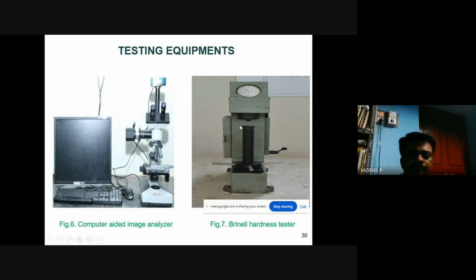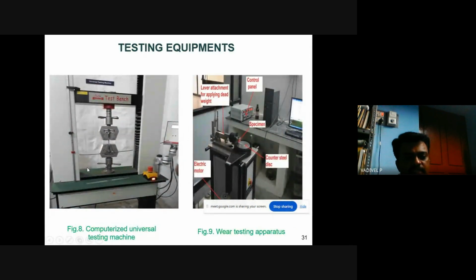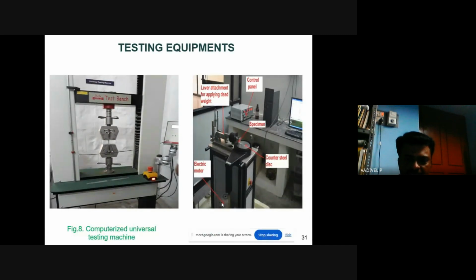Brinell hardness tester, and this is the universal testing machine, and this is the wear testing apparatus. So this is the pin on disc apparatus. Here is the lever attachment for applying dead weight. So dead weight will be applied here, and the panel control is here, and the specimen is fixed. The specimen is round so that it can be fixed in the specimen holder. So this is a counter steel disc. In the disc only the specimen is rotated, and the electric motor is here, which is used to rotate the disc.